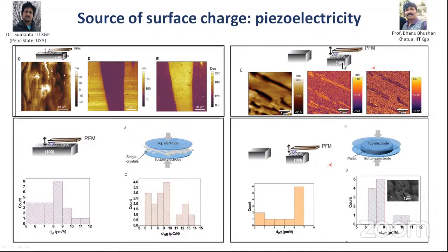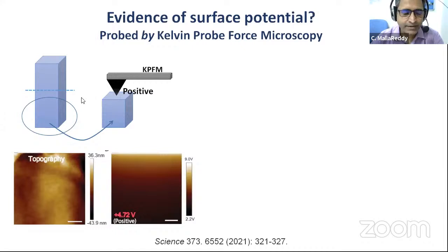Okay. 100 and 010 are crystallographically exactly identical because it is a tetragonal crystal. Yeah. So then we broke a crystal, and we wanted to map the potential, the electrical charges here. So we used Kelvin probe force microscopy. Here, your tip has an electrical bias. I'm not an expert in this, so excuse me if I say something wrong.